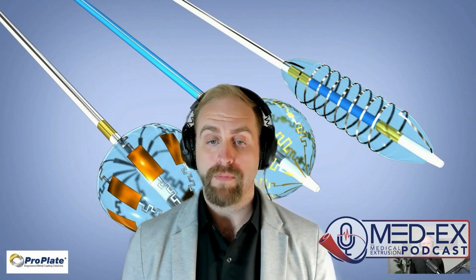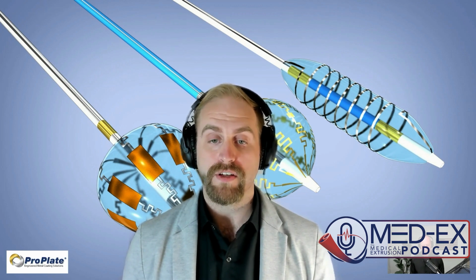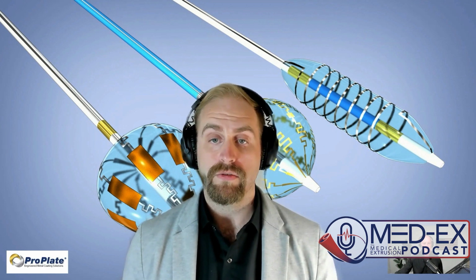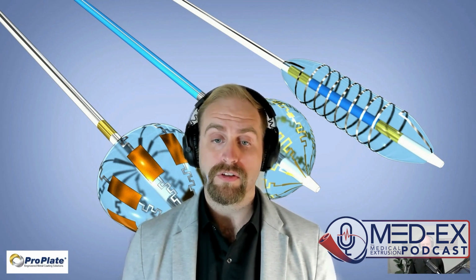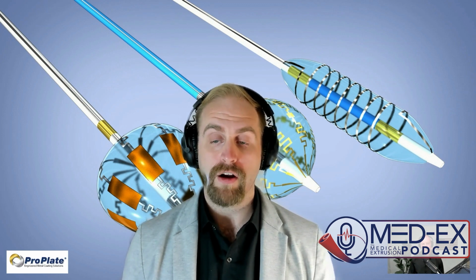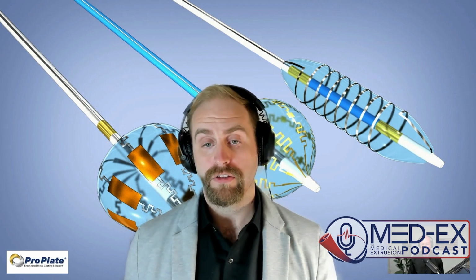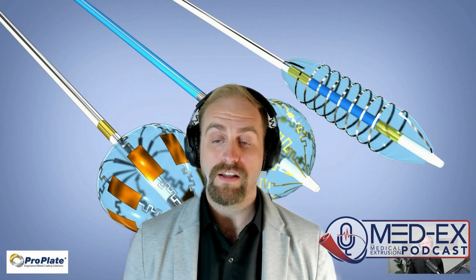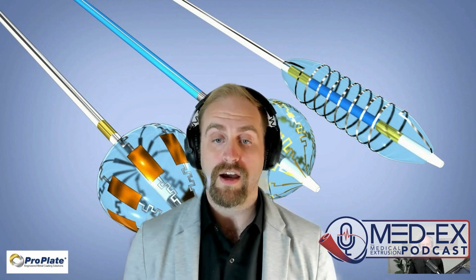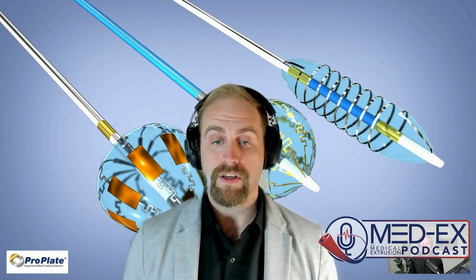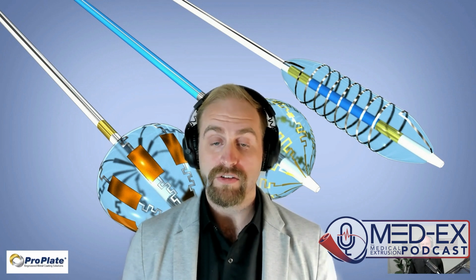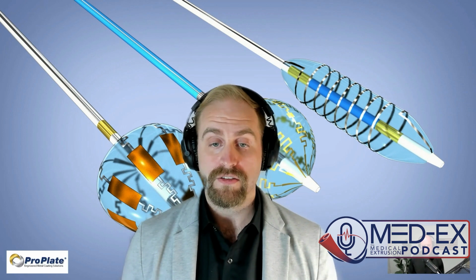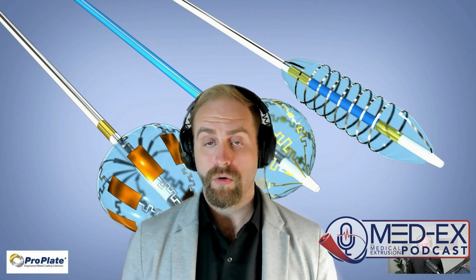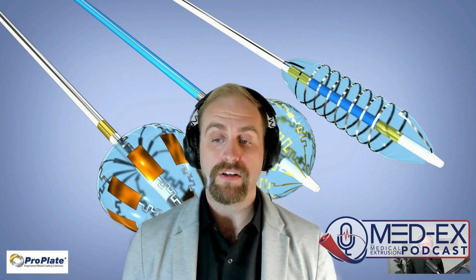In the plating bath, you'll have metals in the form of an electrolyte solution, with ions suspended in this bath. It's an electrochemical process. And you apply an electrical current to the parts through either a rack or a barrel fixture. And in most cases, it's actually a custom fixture that we've built in-house, because most of these parts are so unique and their requirements are unique around them. After applying that current, the parts become the cathode. And in the bath, there's an anode as well, which pushes those metal ions onto the parts, building up microinches at a time. And it's actually a very effective and efficient way to layer metals onto another. With the Vizi-Band process for radiopacity, we're using either gold or platinum, and different thicknesses depending on the application.